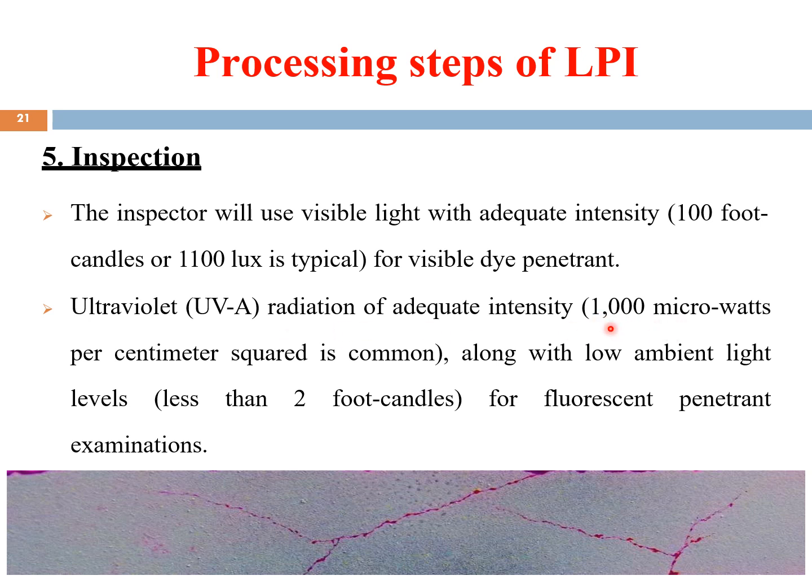It is, I think, yes, 1000 microwatt per centimeter square is common, and that is given as the UV radiation light intensity. The UV light alone cannot be used. The UV light is used in association with low ambient light, less than 2 foot candles, for fluorescent penetrant examination.